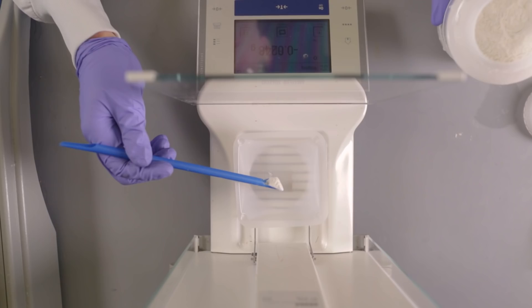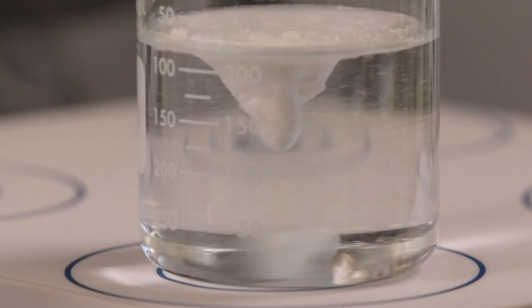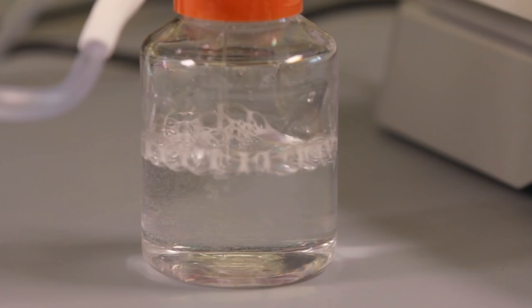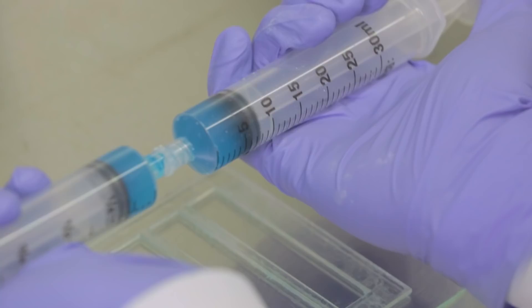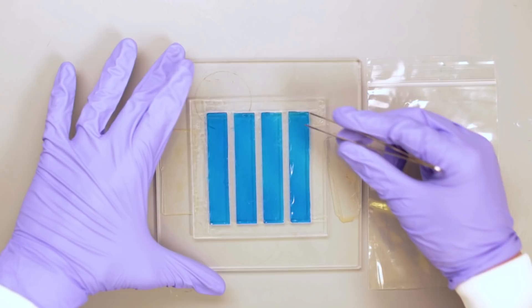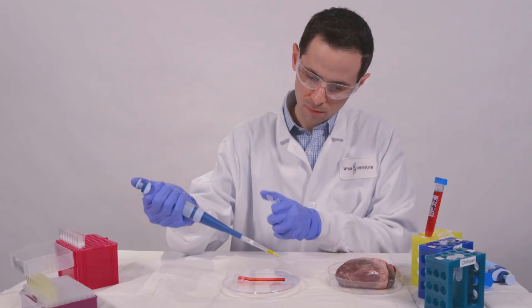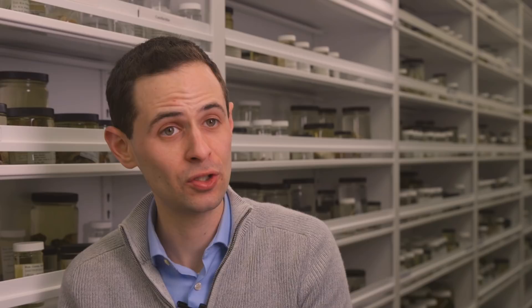The first step is to make the tough gel by essentially dissolving alginate in solution. We purify that alginate solution and then add in some polyacrylamide into some syringes. We do syringe mixing steps and then inject the solutions into molds — we can mold them into any shape we might be interested in. We apply our adhesive components and couple those adhesive polymers to the surface of the gel, which we then apply to our wet tissue. We apply compression for one or two minutes, and as that happens the adhesion energy increases rapidly.